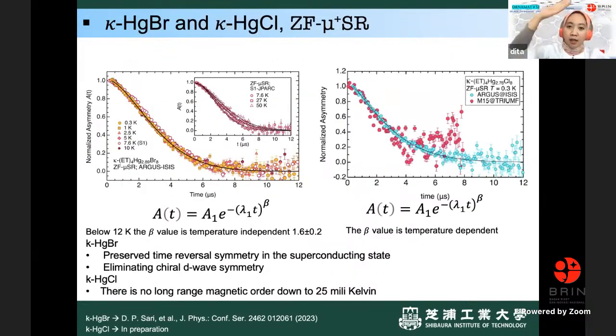You see there is an exponential shape of the spectra, both in the bromine and chlorine, but maybe we see the difference later. From the bromine, there is no difference between the spectra above the superconducting temperature and below it. It's the same spectra above and below the critical superconducting temperature. But for the mercury chlorine, we have a hint that there is no long-range magnetic order, because we don't see the muon spin precession.